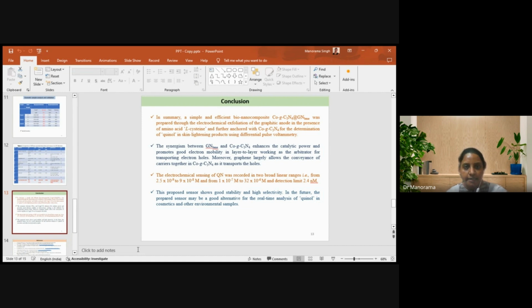Here the synergism between the graphene nanosheet and cobalt-doped graphitic carbon nitride enhances the catalytic power and promotes good electron mobility layer to layer, working as the arbitrator for transporting electron holes. Moreover, graphene largely allows the conveyance of carriers together in cobalt-doped graphitic carbon nitride, as it transports the holes also.